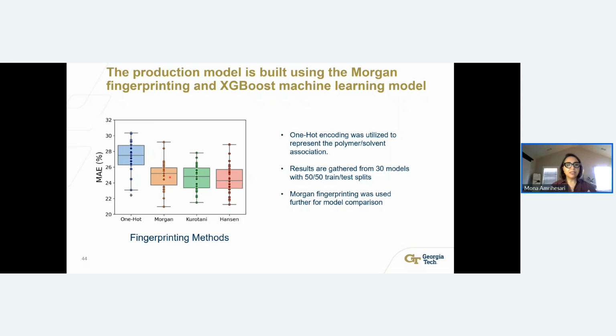Following this method, we then wanted to tell the model what it's dealing with, right? We have the polymers and we have the solvents. How do we teach the machine learning model what it is learning and what materials it's working with? So for the polymer, we used one-hot encoding, meaning that the model knows if the polymer exists or not in the solution. We were at the border of 30 polymers tested.